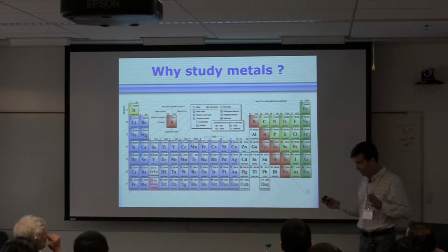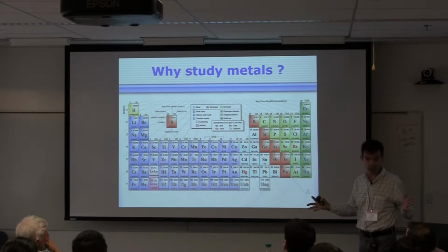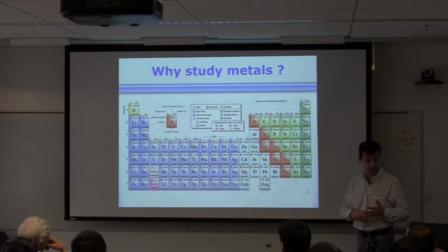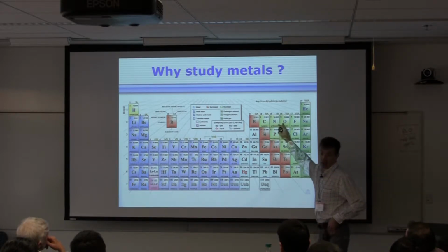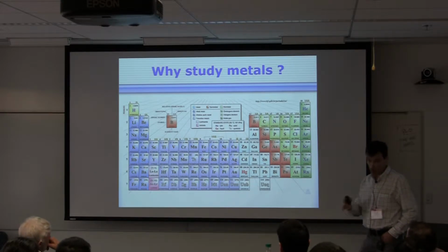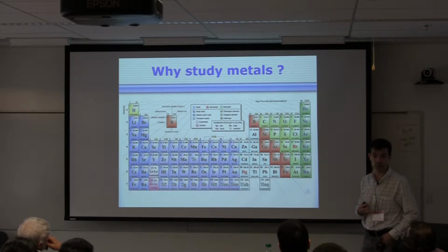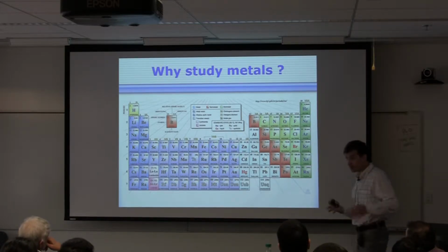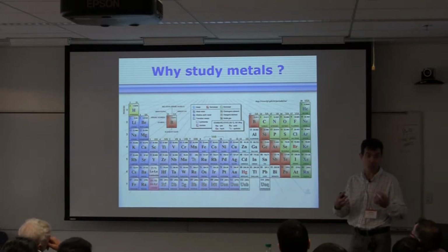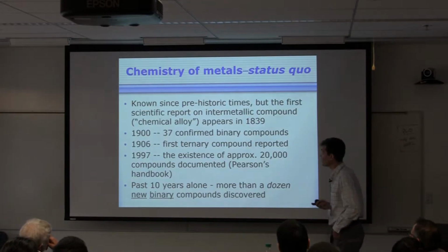So even if you make the same compound twice and you measure the properties, you would be amazed sometimes. Same person, same furnace, same elements, 2 different properties, simply because you might have introduced a small amount of oxygen or carbon or silicon or something else, which unfortunately the analytical techniques that are available to us will not be able to quantify. So these are very important things, and this is where understanding structure and bonding and how to count electrons is actually very important.